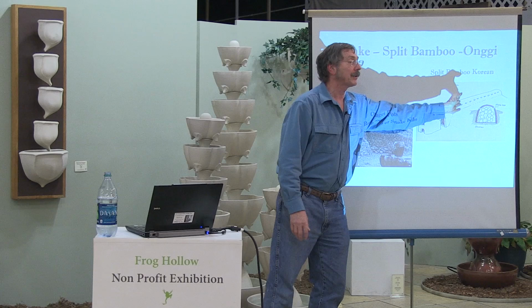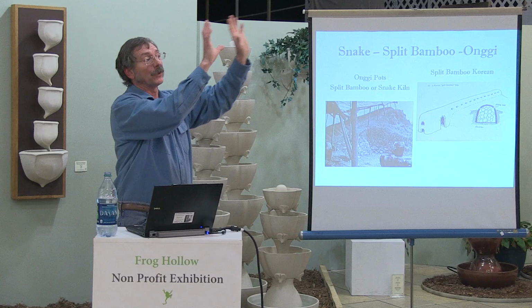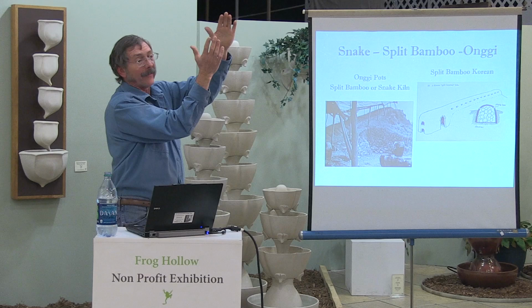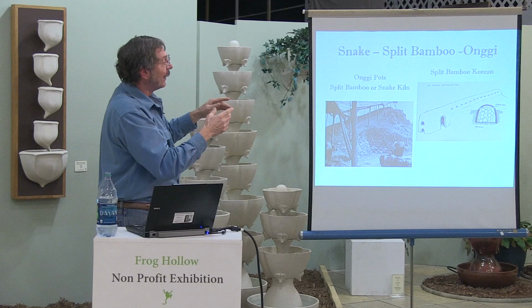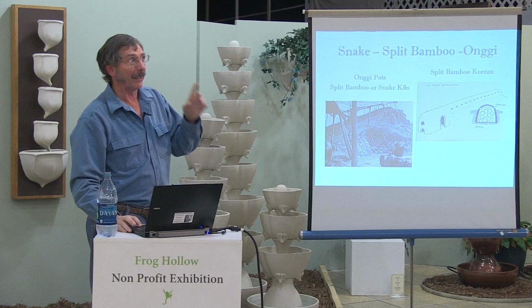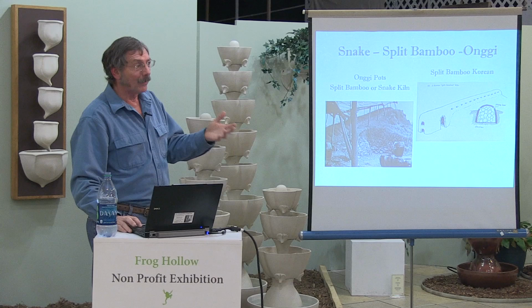By the time you're done firing, you could actually be unloading the bottom of it, because you're pushing the heat up the hill. And it's sort of like laying a chimney on its side. You're inducing the draft by the fact that the kiln is at an angle. 22 degrees is technically the best angle for doing that, but that's essentially what the cave or bank kilns were. And that's become one of the rages, it's become very popular in the U.S. in the last 15, 18 years, is wood firing, especially Anagama style firing.